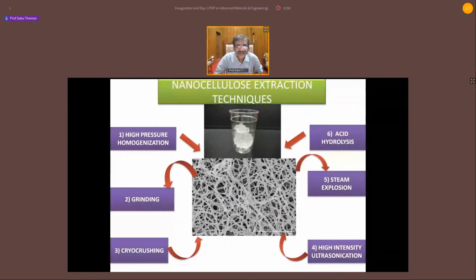If you look at nanocellulose with your naked eye, if you put nanocellulose in a plastic container, you see, it looks like a gel. It's a gel. And if you examine under a high resolution electron microscope, what you really see is a beautiful web of interconnected nanofibers. The diameter of this fiber is in the range of 20 nanometers. Length could be 1,000 nanometers, 2,000 nanometers. It's very difficult to measure the length of the fiber because it's very long.